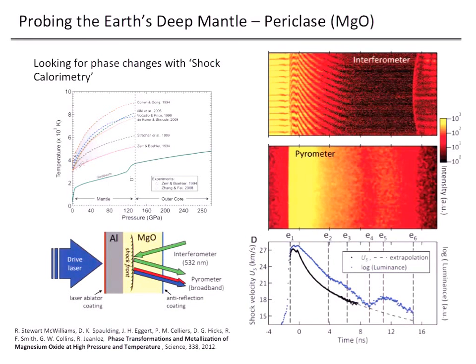So we did decaying shock experiments where we drive a short laser pulse into the back of our sample. We ablate plastic off the back, and sort of in the way that a rocket takes off, that ablation drives a shock wave through the material in an opposite direction. We're looking at it from the right over here with an interferometer, a VISAR system that you saw a version of yesterday in some of the talks, and also with the pyrometry system to look at the thermal emission from the shock front.